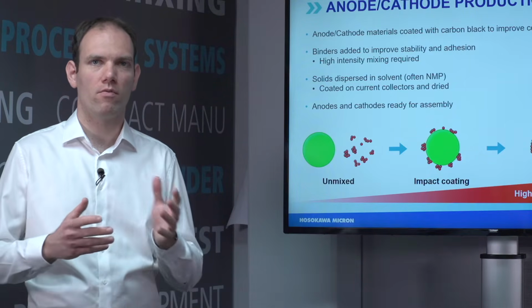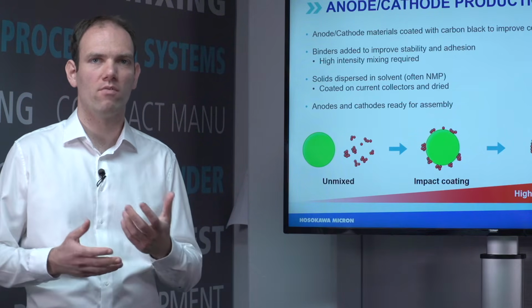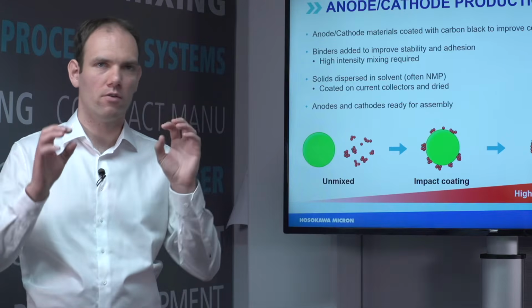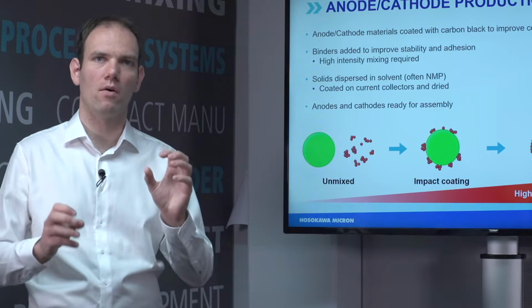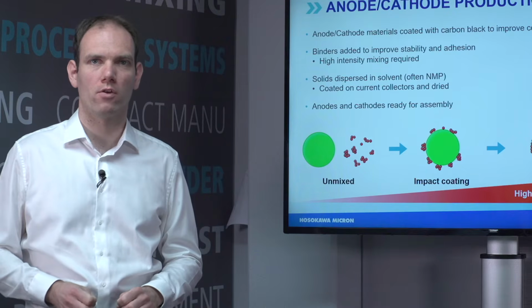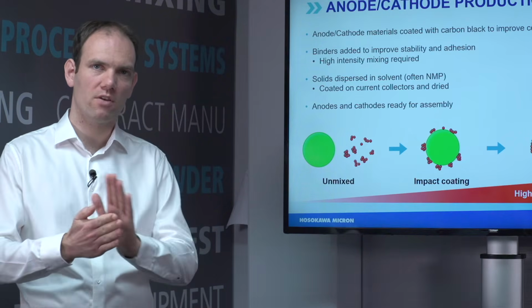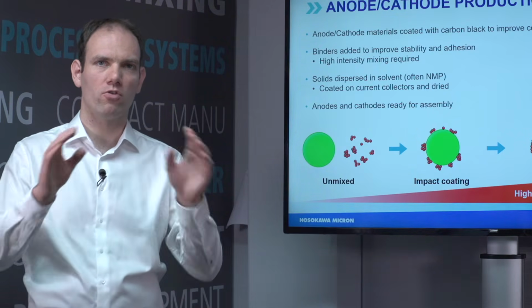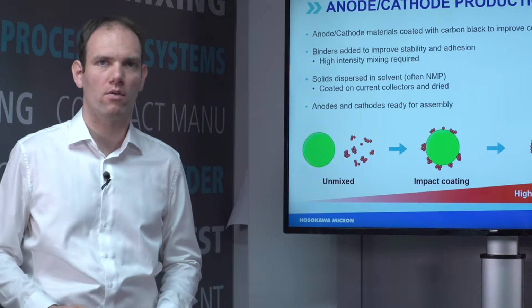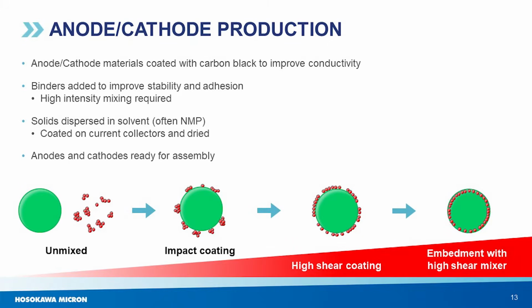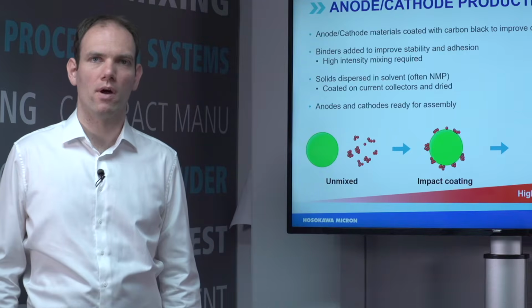And if we mix them only with an impact mixer, then there's a very loose coating around the precursor particles. While if we mix with high shear, the particles coat very well, or are even embedded in the precursor material. This creates a very strong bond between the carbon black and the precursor, which yields very good batteries.